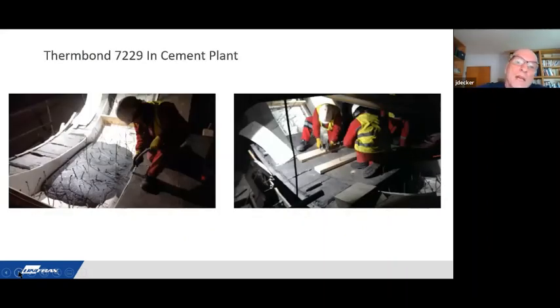And this is a cement plant. It's the ring before the nose block. And that's actually the most challenging application because there's always this push from the furnace lining, which is magnesite and has a very high reversible expansion. So the magnesite lining of the rotary furnace is pushing towards the nose and crushes the ring before the nose block itself. And in this case, they were installing the material at freezing temperatures. It was very cold, and so they were struggling a little bit with the setting time because it takes longer for the material to set at those temperatures.